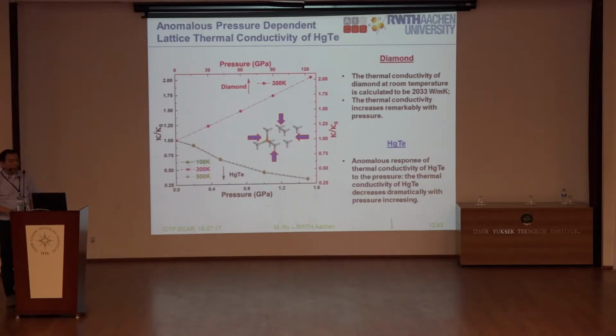And then fortunately we found a typical example, the AB compound mercury telluride. We found this mercury telluride is very special. Here is the relative thermal conductivity change as a function of pressure. If you apply the pressure, the thermal conductivity goes down quite significantly: up to about 1.5 gigapascal, thermal conductivity is reduced by more than 60%, which is significant, right?